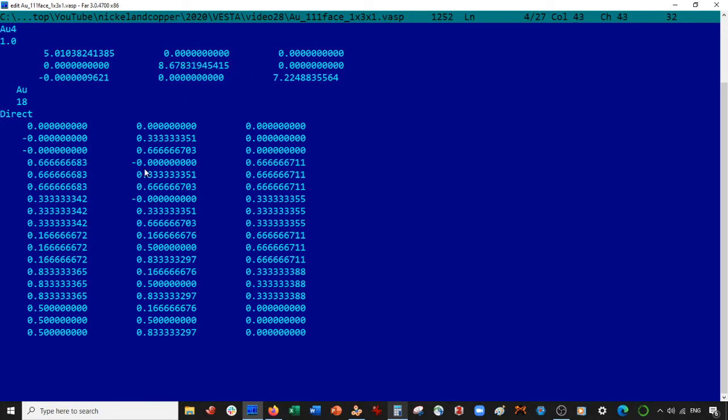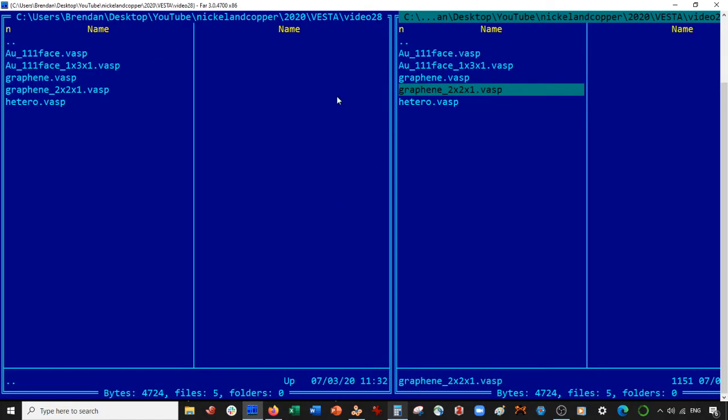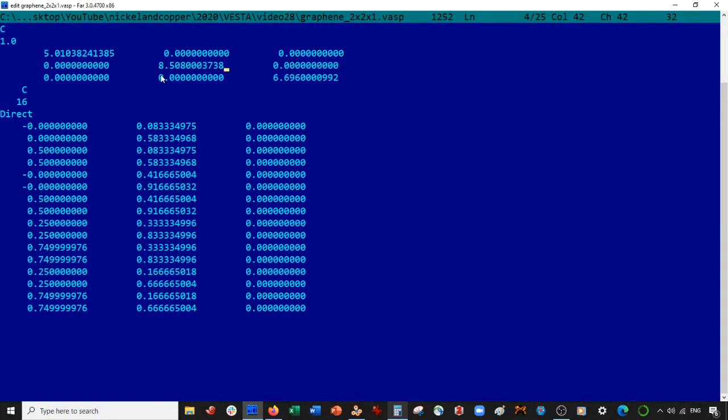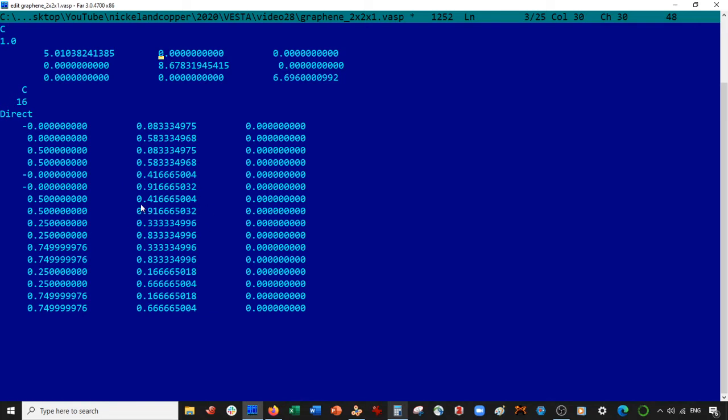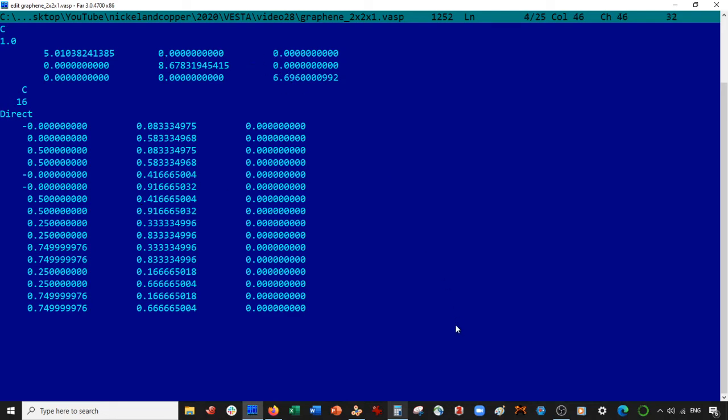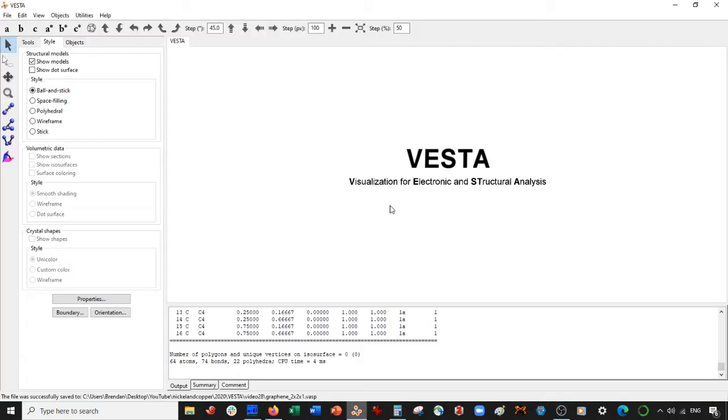Now these are the new coordinates for the B dimension for both crystals. Because the coordinates down below are in fractional coordinates or direct coordinates, the coordinates are with respect to the vectors. So what happens is this basically disperses the atomic displacement from the mismatched lattice vectors over the whole crystal and makes it much more well behaved when you have to relax the heterostructures later.